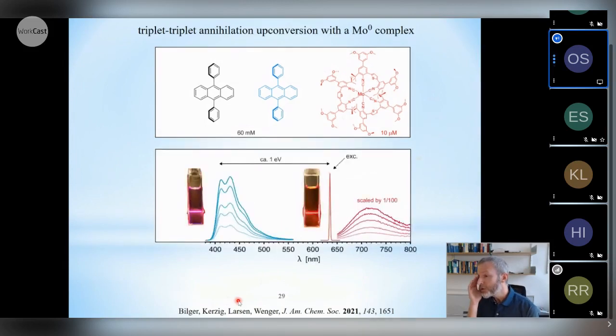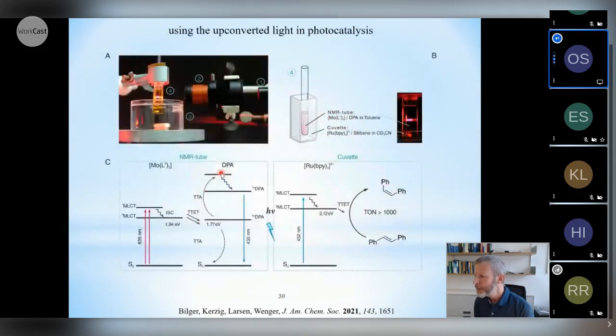And you see here how this looks like in reality. You see this is basically the red excitation light coming from the 635 nm CW laser here. Then the prompt luminescence usually dominates in these schemes here, so I had to scale this down by a factor of 100. But in presence of diphenylanthracene, then you will see a violet emission here, at least on the CCD camera of the iPhone or whatever it was. And so there's a fairly sizable shift here between excitation wavelength and the first vibronic member here of the delayed fluorescence that is occurring. And then the guys did something that I thought was really quite neat.